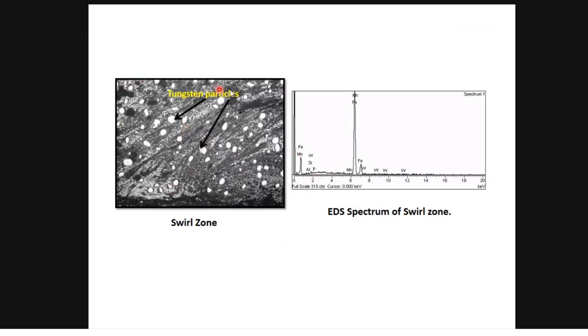In SEM, we found a lot of, in the stir zone, especially in the stir zone region, we found a lot of white spots. So these white spots, by using EDS spot analysis, we found that these are all tungsten. Because we used tungsten as a tool during this friction stir welding, the tool material has worn out. The worn out particles or debris are deposited all over this stir zone.